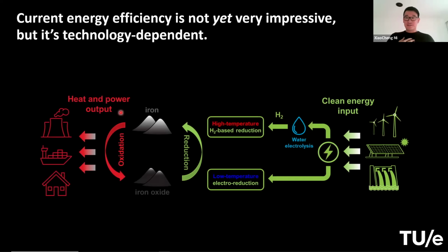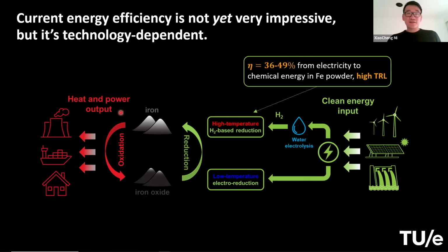So up to this point, you may start to wonder, okay, you said a lot of good things about this iron power cycle. What is the overall energy efficiency, right? To be honest with you, so far, this energy efficiency is not yet very impressive, but this is technology dependent. So let's look at it part by part. For this hydrogen-based high temperature reduction, the energy efficiency is not very good because you need to go through two steps. You need to first do water electrolysis to generate hydrogen, and then you do hydrogen reduction at high temperature, for which you need to heat up the system. So the electricity to chemical energy stored in iron powder is around 40%, right? But this has a relatively higher TRL. That means we are already working on the upscaling of the technology.